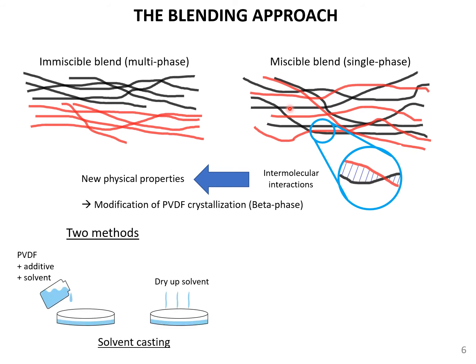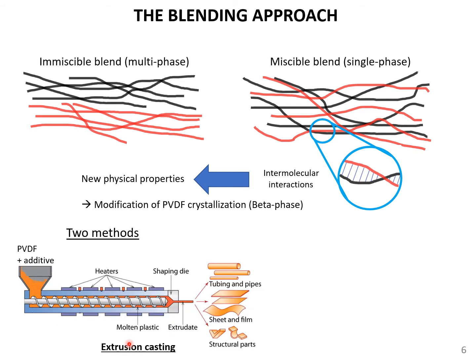To obtain this type of blend, there are two main approaches. The first, based on a solution that you make from PVDF and an additive, in this case another polymer, that you solubilize in a common solvent, then evaporate to obtain a dry film. Or you have a second approach based on extrusion technology. In this case, you start directly from solid particles like PVDF that you add at the hopper, you melt all the particles or additives, and you obtain from the die different geometries like a tube or a film.